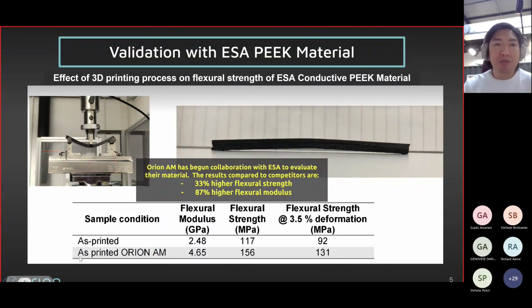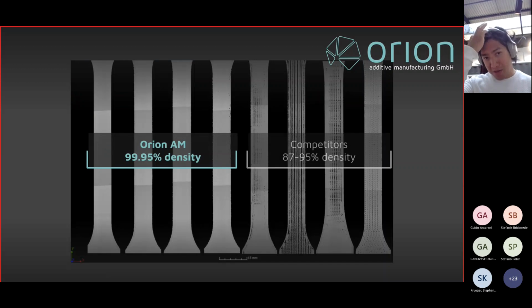The as printed was actually with one of our competitors' technologies, and as printed, Orion is using our technology, and we were able to increase the flexural strength by 33%, and the flexural modulus, or the stiffness of this material, by up to 87% using our technology. So this was really great validation, for us and also for ESA, to show what is capable using this material with our process, and it opens the doors for more opportunities into applications in space. A little bit more on that later.